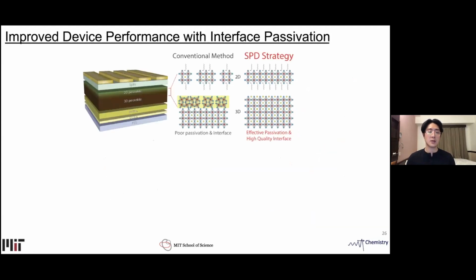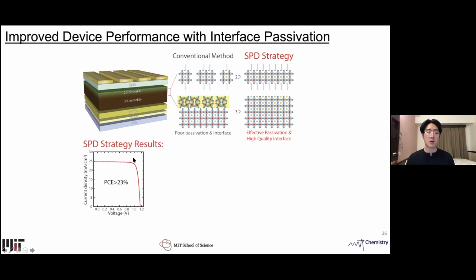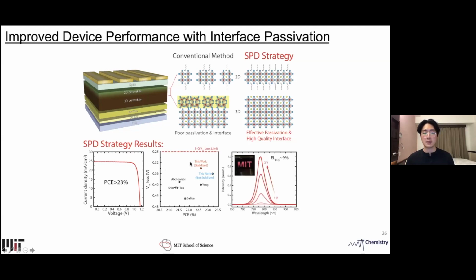With the SPD strategy developed for 2D perovskite passivation, we were able to achieve a higher quality 2D perovskite passivation layer along with a stabilized interface. This resulted in a high power conversion efficiency and also a low VOC loss, where the lower the VOC loss, the higher the radiative efficiency. This is also supported by a high electroluminescence efficiency.